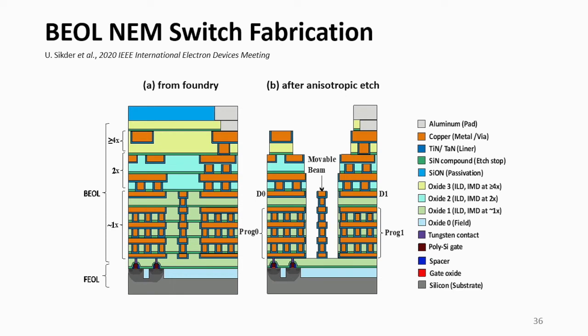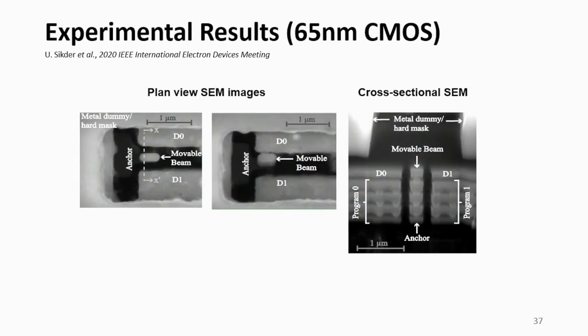Well, my student has just used a standard PDK. We've done this in 65 nanometer CMOS technology, and then more recently in 16 nanometer CMOS technology. What she does is she patterns the upper layers of metal to serve as a mask for anisotropic etching away of the dielectric that's surrounding that movable electrode. So after we receive the chips back from the foundry, we process them in our nanolab to do a dry etch. It's actually a multi-step etch to release that beam so it can move back and forth. And here's the initial experimental results.